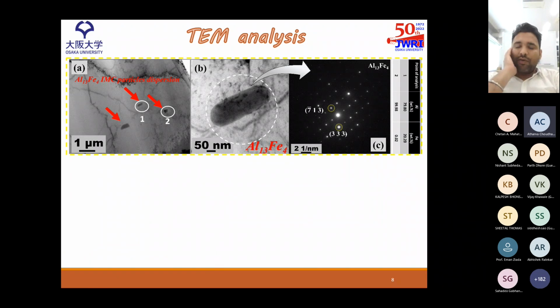Now coming to the high magnification transmission electron microscopy, we have obtained a sample from the stir zone. As already said, in the top section, the stir zone is a particle deficient region. So there is no iron for the diffusion or the reaction with aluminum. So that's why we have observed only very few IMC particles here. And this is a well-defined elliptical shaped Al13Fe4 IMC particle. And on SAED indexing, we have confirmed this particle as the IMC particle, and also the EDS analysis further confirms it.